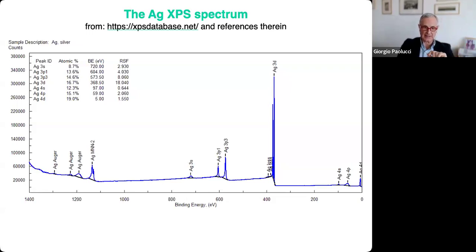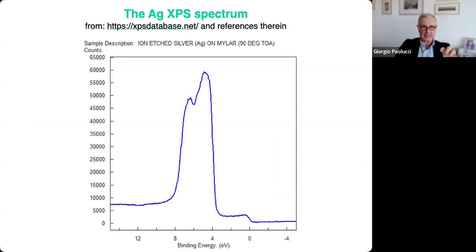And all these peaks are related to, apart from the low energy ones, which are called Auger, and I will not go into the details of Auger spectroscopy, but all the others are related to electronic states in the silver sample. So you see the silver 3d at about 368 eV, and you see the valence levels, which are mainly formed by the 4d states, and so on and so forth. This is the zoom, if you wish, of the same spectrum close to the Fermi level, which is the zero of our energy scale.